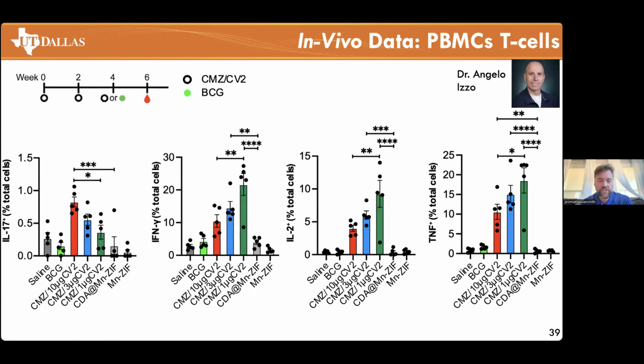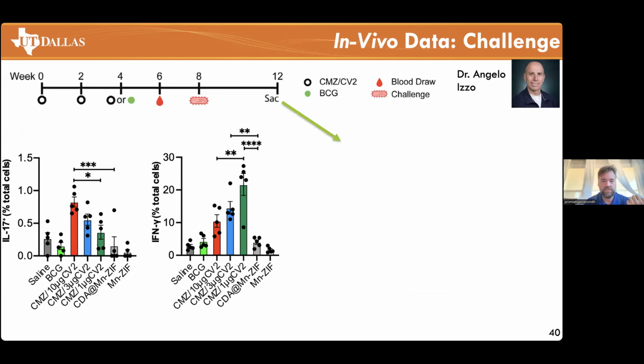We did an infection in vivo. So essentially we did an initial inoculation at week 4, and we looked at some cytokines that are associated with activation that we wanted to look at for tuberculosis. And essentially what this data shows is that it does a really great job. You can see BCG down here, the little bright neon green, actually doesn't induce that many cytokines, whereas ours stimulates a very strong intracellular type immune response. And so that's great. It suggests it should work.